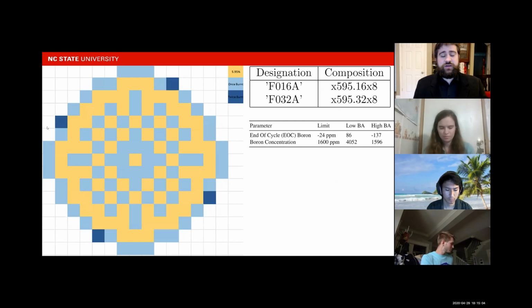After we examined that, we wanted to check if it was possible to have a viable reactor with enough reactivity to make it through the full cycle length while also having the boron concentration within limits. We checked this by determining the minimum enrichment for a full core to have the desired cycle length. We created fuel assemblies with as little boron or gadolinium as possible, and then we increased it to the maximum amount to see if the initial reactivity could be brought within limits. Since it couldn't, we determined that we needed more burnable poisons in our assemblies. To make that possible, we requested the cross-sections from Framatome, and they provided them.